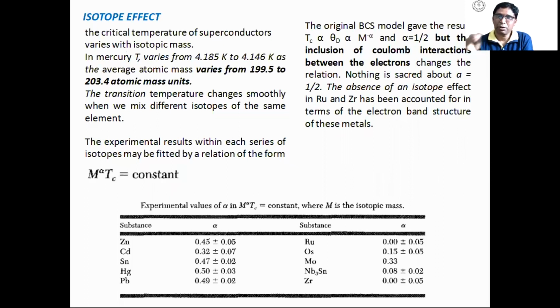So it is observed that the critical temperature for the same element also changes. For example, if you consider mercury, the atomic mass varies from 199.5 to 203.4 atomic mass units. In that case, you will see the critical temperature Tc varies from 4.185 Kelvin to 4.146 Kelvin.